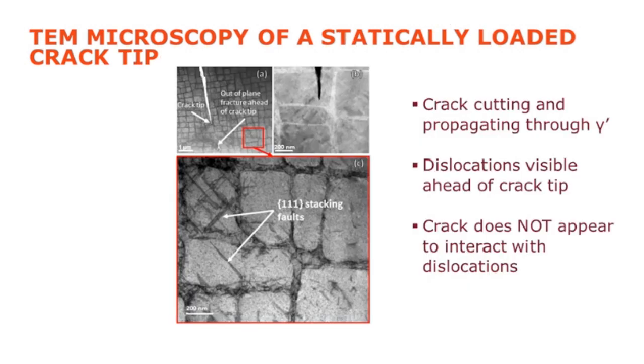So looking then at some higher mag images, so these are transmission electron microscope images of the crack tip. What we can see is the crack cutting through and propagating through the gamma prime, quite interestingly, because again, just to highlight, those gamma prime phases are strengthening, so they're quite a lot stronger than the gamma. We can also see dislocations, so stacking faults on the octahedral planes, so 1-1-1 stacking faults ahead of the crack tip. Again, that's not unexpected at these temperatures.